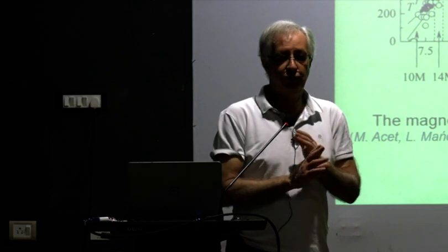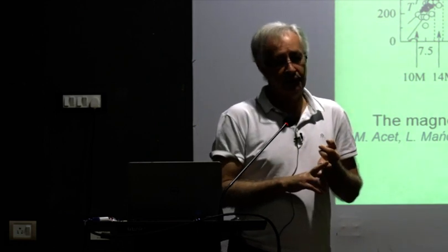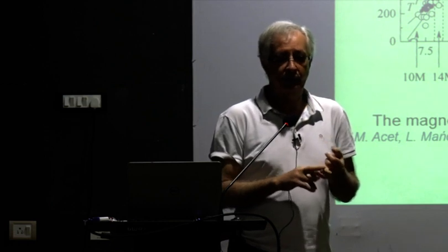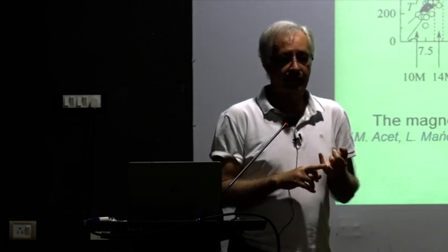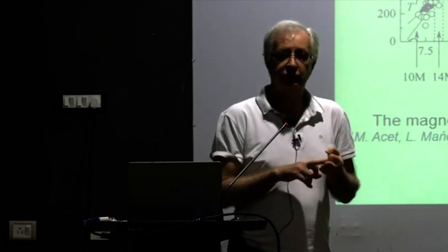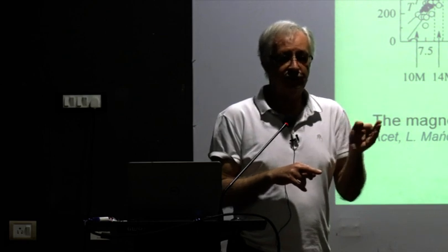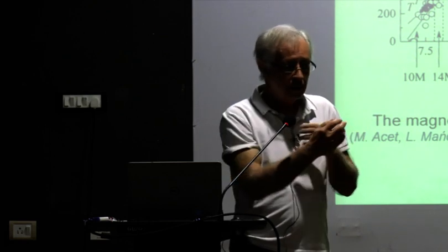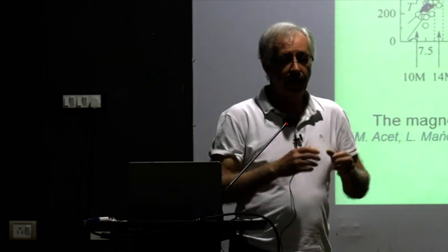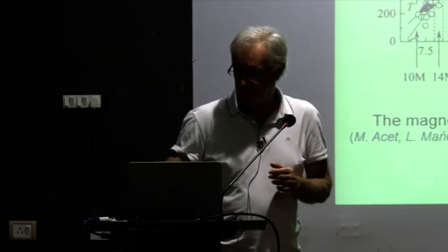So instead, what do you do first? You do more conventional measurements first, like magnetization and resistivity. You try to see what you have in your magnetization. You try to see what you have in your resistivity, and then you do your X-ray measurements at special positions, and then you try to iteratively understand which transitions are located.